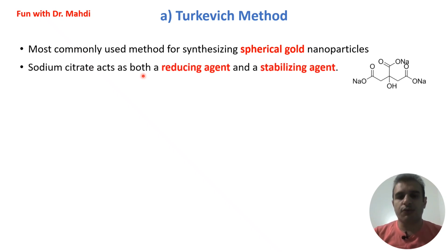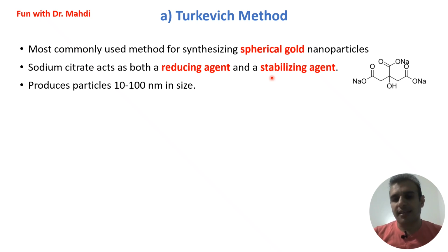And also you need to use sodium citrate. So you can see the structure of sodium citrate. Sodium citrate can act as a reducing agent and also as a stabilizing agent. The size of nanoparticles in this method is between 10 to 100 nanometers.